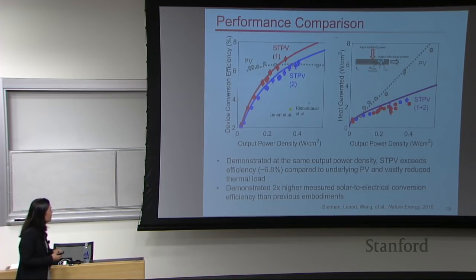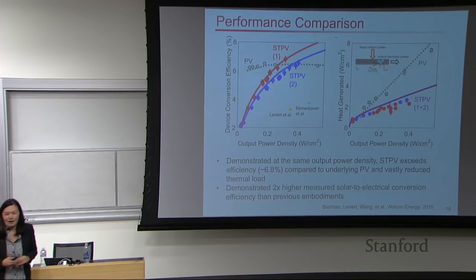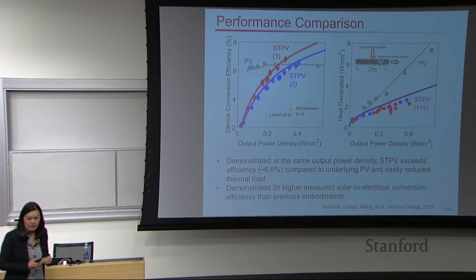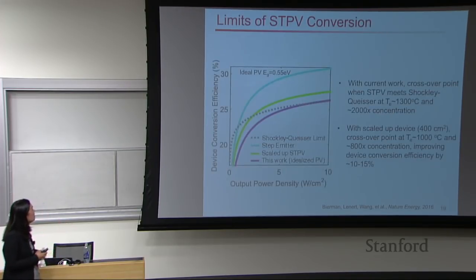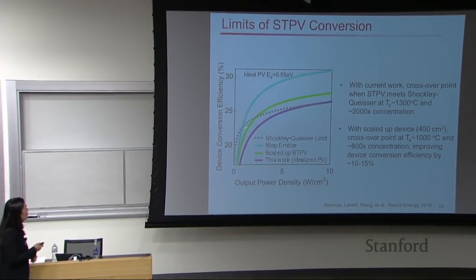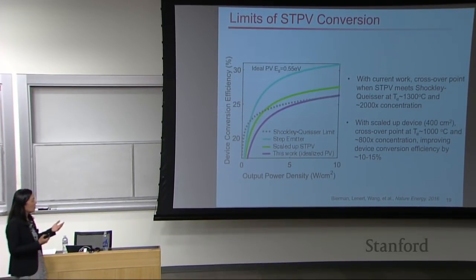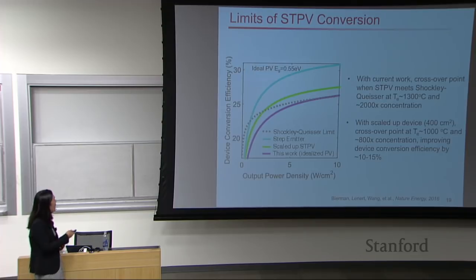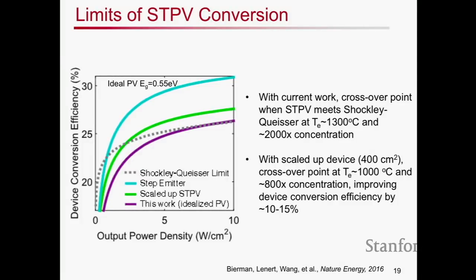So we've now demonstrated an efficiency closer to about 7%. Again, we're still quite far from the theoretical limits, and we think there is a path forward. This is what I show you here, a plot again of the device conversion efficiency, assuming that we have an ideal PV cell. So we're not working on the PV itself yet. This is a function of the output power density. And what I show here in the dotted gray line is the Shockley-Queisser limit, again. What our work has shown based on these models is that with an idealized PV cell, this is where we are in this curve, right? So certainly at some point we can reach where we are in terms of the Shockley-Queisser limit.